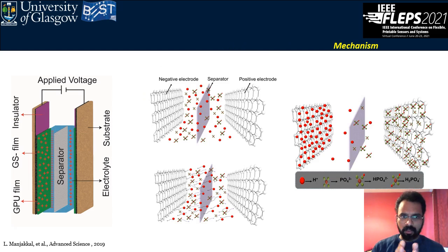And further, we fabricated two such electrodes and applied a potential between them. You can see here that there is a GPU film, graphene polyurethane film, and graphene sheet, and depending on the polarity of the applied voltage, the ions from the phosphoric acid, which contains H plus and PO4 3 minus or different negative ions, are distributed depending on the polarity of the electrodes. For example, before charging, the ions are distributed all around the separator, and once we charge the device, towards the negative electrode positive ions are attracted through electrochemical double layer formation, and you can see here that the ions are distributed around the surface of the electrode.